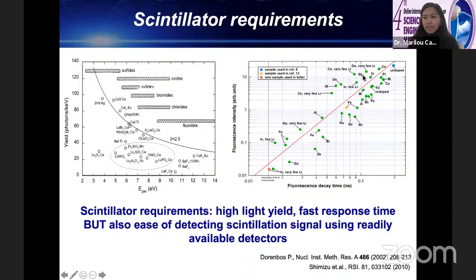So if we want a very intense, bright scintillator, we'll usually have to sacrifice response time, and you have here a slower response time. If you want a very fast scintillator, then you'll have to deal with very low light intensity. So in some applications, you want a fast scintillator, for example, if you're using time of flight. In other applications, a slow scintillator is enough, if, for example, you're using it for dosimetry.